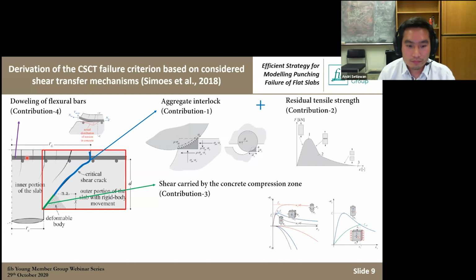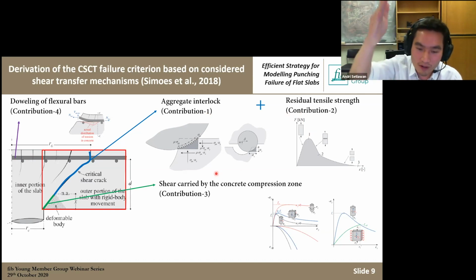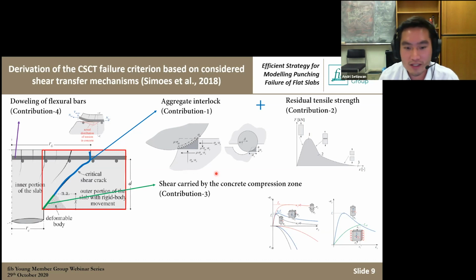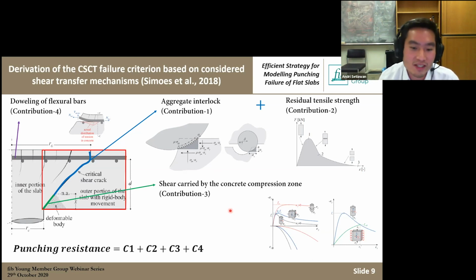So for a certain crack opening, you know the crack displacement and crack sliding, you can calculate the contribution of each, and then you integrate them along the assumed crack surface, you get the resistance. So you do this for the next crack opening, and then you get the failure criterion. So basically, the punching resistance is simply the integration or the total of each contribution along the critical shear crack. For those of you who are interested, you can refer to Simoes et al. studies, which completely describe this derivation.